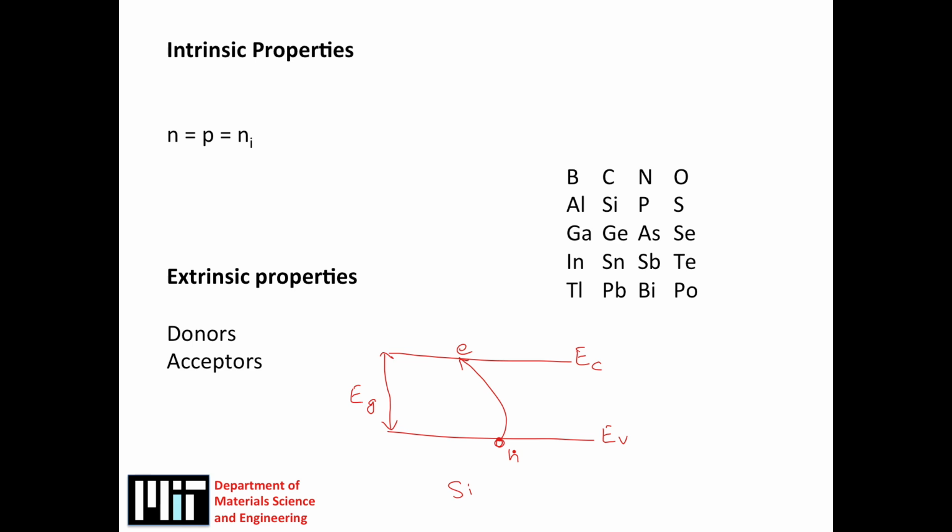So the band structure gives us a convenient way of thinking about where, in terms of energy, the carriers are, and also where in terms of position. This axis, of course, is energy, and this axis here is position, a spatial location. So in the case of doping of silicon, for example, if we have a concentration gradient of dopants so that we have a lot of dopants on the left and very few on the right, then we can actually represent that by changes in the band structure as we go along the material. So this is the case for the intrinsic carrier.